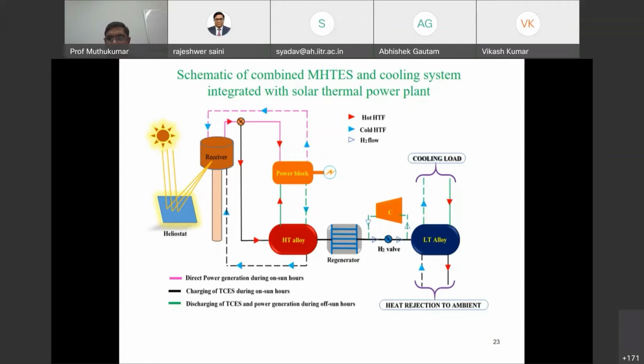Whenever you need the heat, say during night time, with the help of a small compressor, you can desorb the hydrogen from this low temperature alloy. You desorb the hydrogen from the low temperature alloy at about 1 bar pressure. Okay, and deliberately I'm going for low pressure. When you reduce the desorption pressure of the low temperature alloy, automatically the desorption temperature will reduce. Now if you desorb the hydrogen at about 1 bar pressure from the low temperature alloy, then it can produce the cooling effect at maybe around 10 to 15 degrees Celsius.